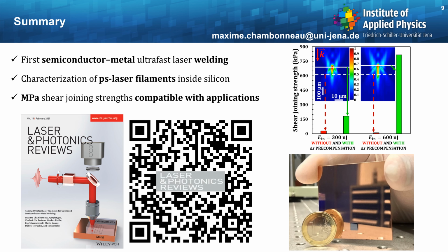To summarize, we have demonstrated the first semiconductor-metal ultrafast laser welding by characterizing picosecond laser filaments inside silicon. We have achieved megapascal shear joining strengths that are compatible with applications,